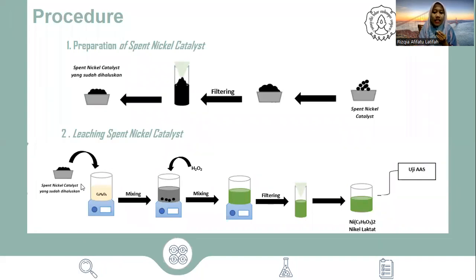The first procedure is the preparation of spent nickel catalyst. The spent nickel catalyst is crushed and then filtered using a sieve. After that, the lactic acid is heated to a temperature close to 80 degrees Celsius. The catalyst was added. The solution is heated and stirred. After 5 minutes, 30 ml of hydrogen peroxide was added. The solution was stirred for 3 hours at 80 degrees. When finished, the solution is filtered and the filtrate is tested using atomic absorption spectroscopy.